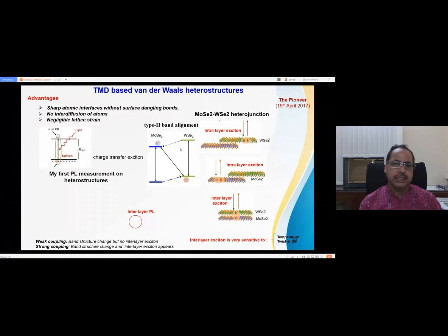So the TMD heterostructure has a type 2 band alignment. In semiconductors, you can see there are three types of band arrangement: type 1, type 2, and type 3. In the type 2 band arrangement, the conduction band minimum belongs to one layer and the valence band maximum belongs to this layer. This is called the staggered band alignment. So there is a band offset. So when you shine the light, electron will go from here to here. Similarly, hole will go to here. Due to this band offset, the electron will relax to here. Similarly, the hole will relax here. So there is an electron and hole pair formation in this direction, spatially indirect. This is called the interlayer exciton, where electron and hole belong to two different layers.